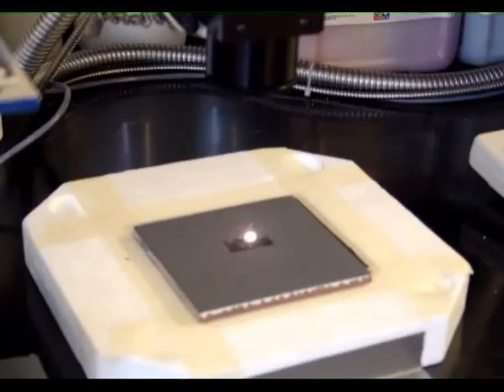On glass, mark at about 20% power and 10% speed. Some experimentation may be required to achieve best results.